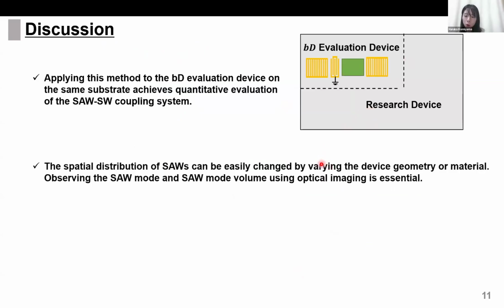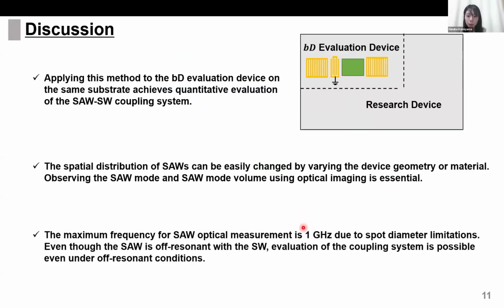Since the spatial distribution of surface acoustic waves varies depending on device geometry and materials, confirmation of surface acoustic wave modes and evaluation of mode volume by optical imaging is essential to progress research quantitatively. And one problem that has prevented the introduction of optical imaging is that the optical spot diameter limits the maximum frequency of surface acoustic waves to about 1 GHz, making them off-resonant with spin waves that have frequencies above GHz. But this study shows that it is possible to evaluate coupled systems even if they are off-resonant.